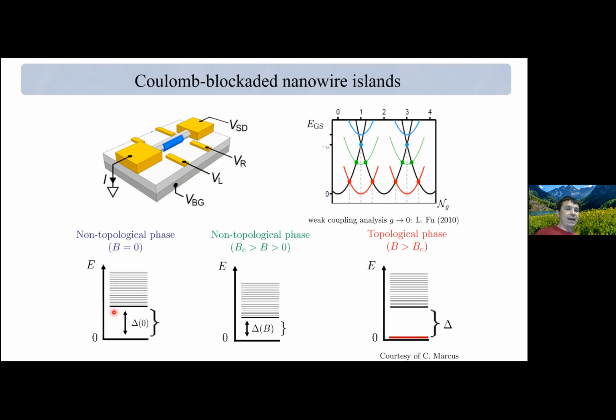So if you have just an s-wave superconductor, we know that the ground state in that case is 2e periodic. And so we expect to see changes by 2e. However, when we have a spinless p-wave superconductor, ground state degeneracy can accept these single electrons. And so this even-odd effect, the difference in the even-odd effect, almost vanishes up to small corrections which appear due to the finite energy splitting. And the topological scenario predicts that this finite energy splitting should be exponentially small.